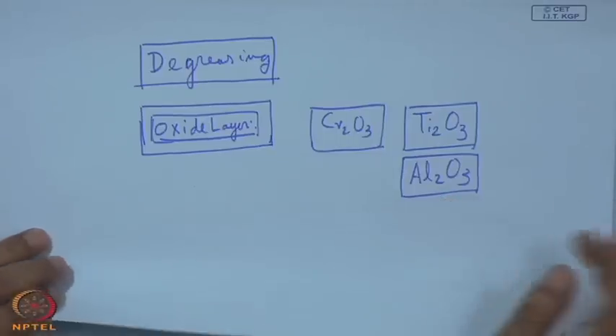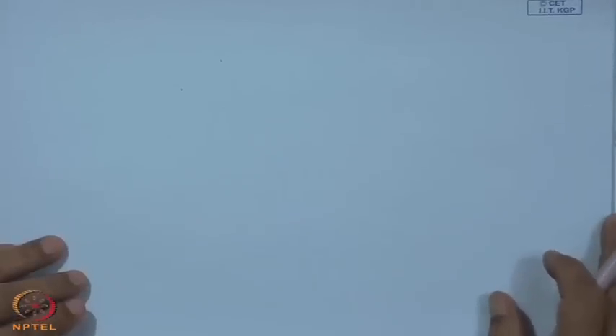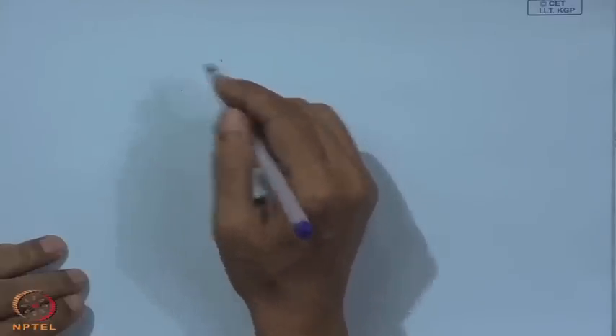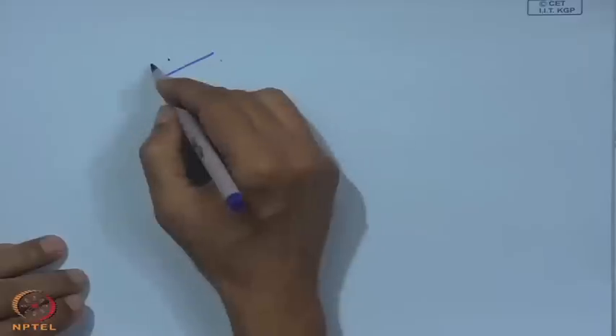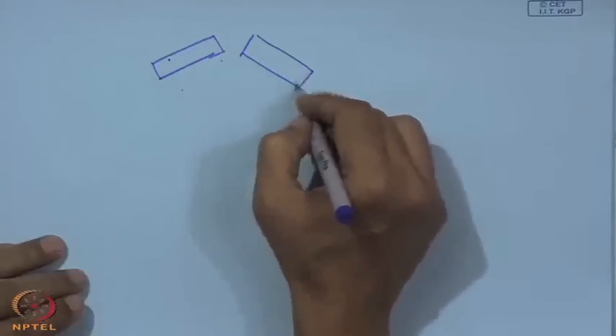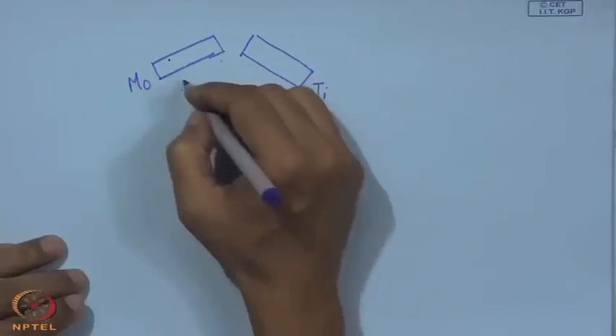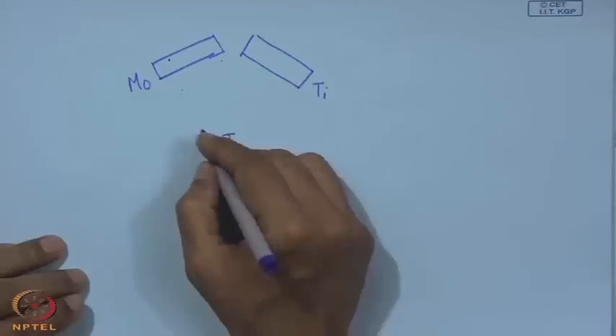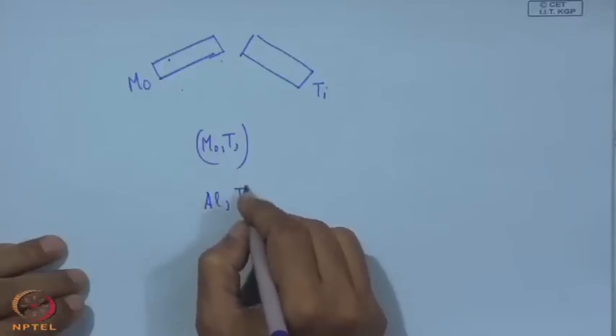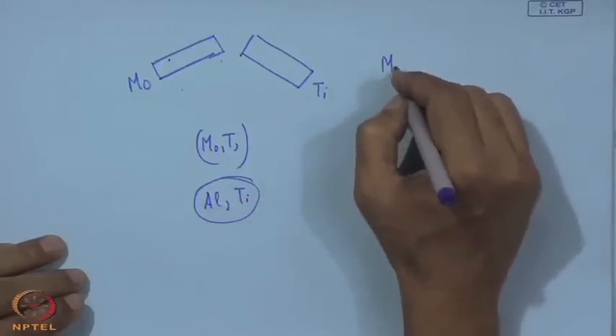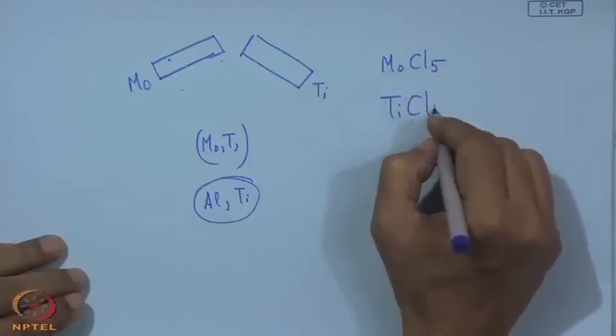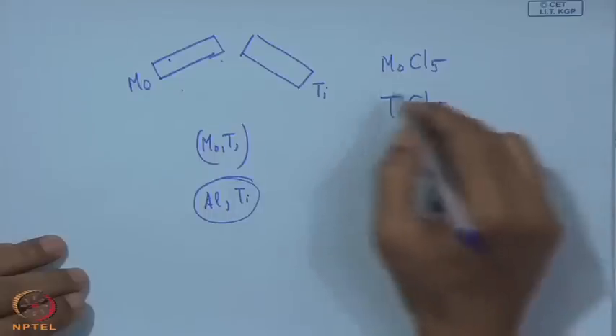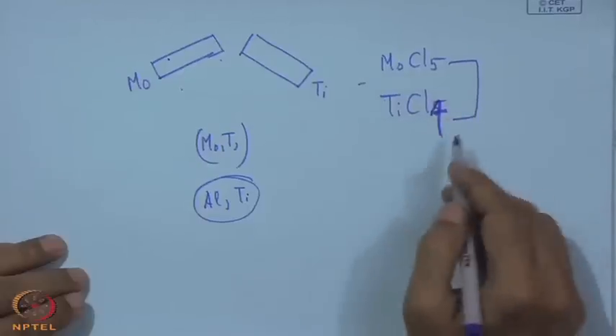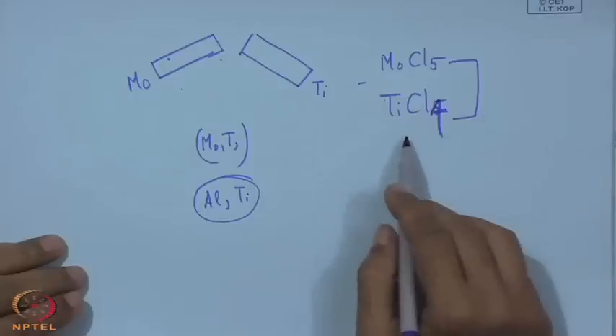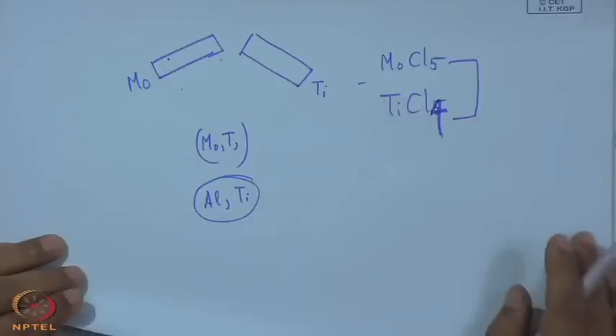Now, co-electrodeposition. Co-electrodeposition means, say for example, we can give this example: in sputtering, we can have two targets, say molybdenum and titanium. So, with two targets we can have molybdenum and titanium, or aluminium and titanium co-deposition is possible. Even by CVD we can have MoCl5 and TiCl4, tetrachloride, both can be brought to the reactor, we can add something more, and with that we can have a co-deposition of this coating over the substrate surface. So, that is not uncommon.